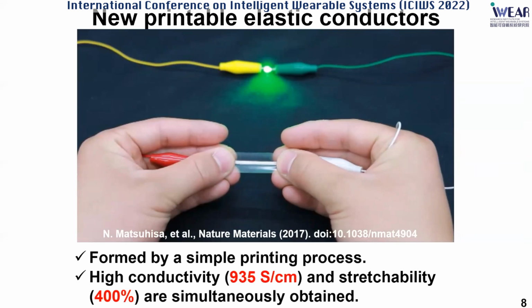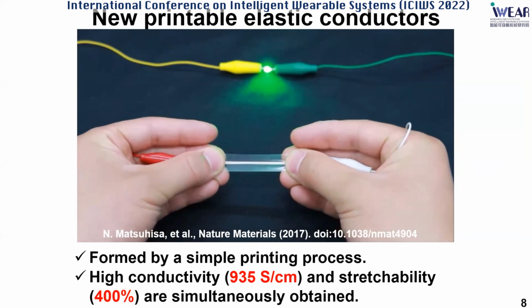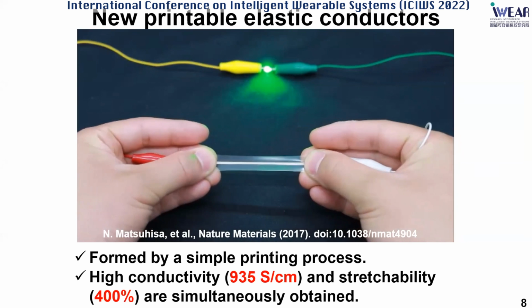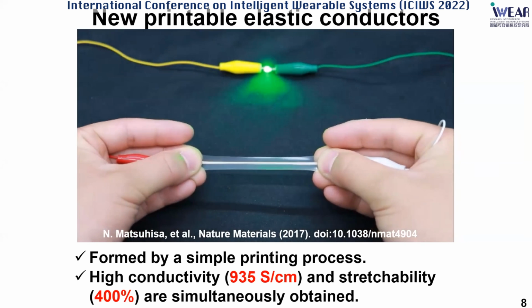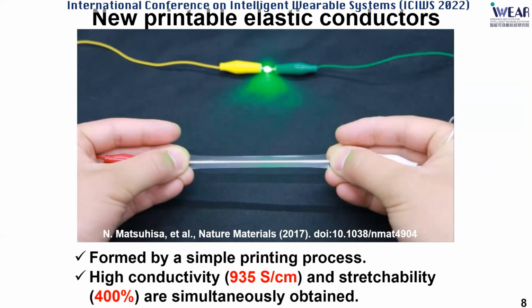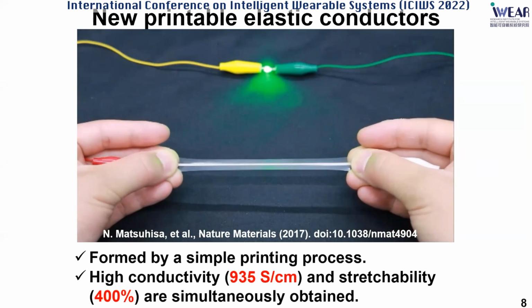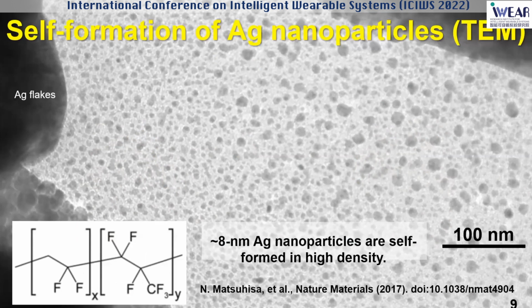In that development, elastic conductors were newly developed, and they achieved high conductivity and high stretchability simultaneously. The ink formulation was very straightforward. We add silver flakes with a typical dimension of 2 to 3 micron to a fluorinated copolymer, mixed them together, printed on an elastic substrate, and annealed at 140 degrees Celsius.